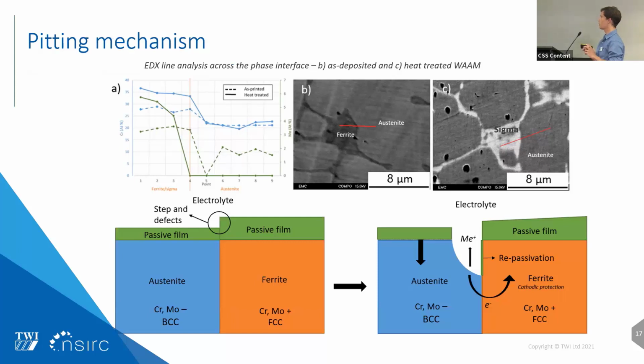So here we've performed some line analysis across the ferrite and austenite interface, and across the sigma and austenite interface. You can see here on this diagram the molybdenum content in green and the chromium content in blue. We see that we have a molybdenum depletion at the vicinity of the ferrite and the sigma, with the depletion zone being wider in the case of the sigma, which is normal since sigma is more molybdenum rich than the ferrite. So what is happening is we have preferential attack at the ferrite and austenite interface.